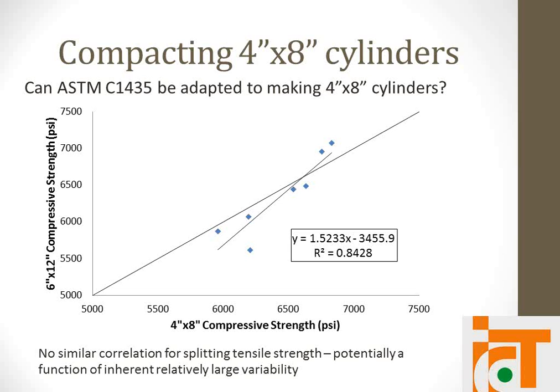Some of the other mixes that have been done where the gradation wasn't controlled, this relationship doesn't exist. It's possible that it's due to segregation, or it could be larger aggregate sizes that are affecting the relationship between the two. That's something else to look at. But we can relate the two, and with more testing, it could be brought up to ASTM to possibly include the 4x8s.